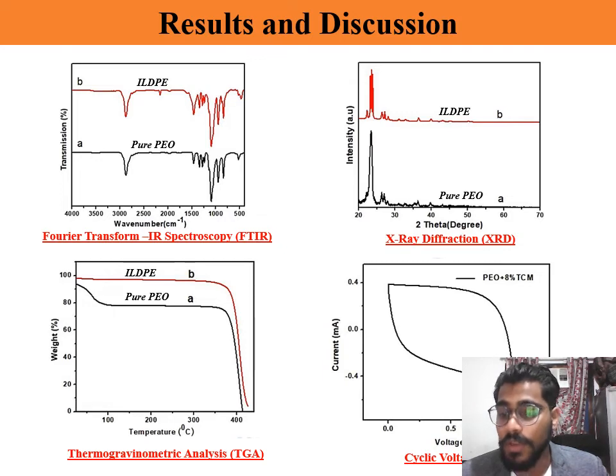It is clearly seen that there was no major weight loss up to 350 degrees Celsius. Beyond this temperature, polymer PEO completely degraded at 400 degrees Celsius, whereas in the ion-doped PEO matrix, as shown in the given figure, the SPE film was stable up to 380 degrees Celsius and completely degraded at 400 degrees Celsius. The increase in the thermal stability of the ion-doped SPE suggests that the effect of the ion on the thermal stability after incorporating with the polymer matrix increases by 20 degrees Celsius.